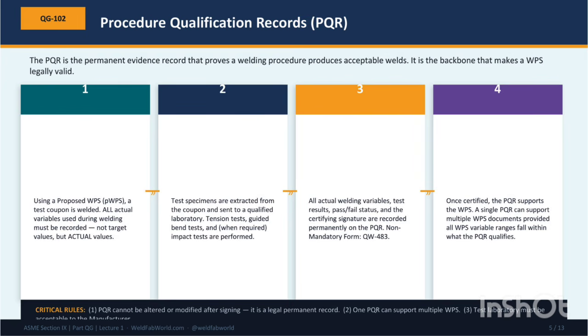Step 2. Mechanical testing. Test specimens are extracted from the coupon and sent to a qualified testing laboratory. At minimum, you will perform tension tests and guided bend tests. When the referencing construction code requires it, and for many pressure vessel applications it does, you also perform impact tests to evaluate toughness.